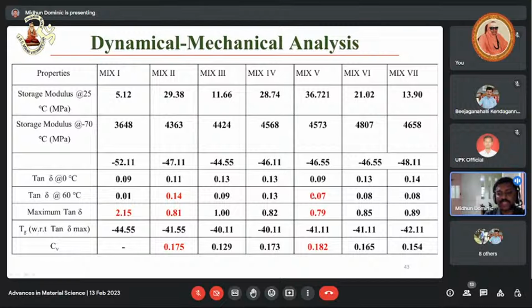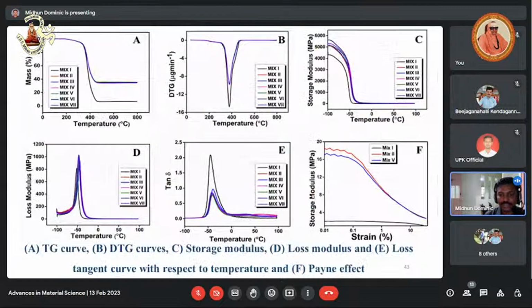About 50% decrease in tan delta at 60 degrees Celsius can be obtained by the synchronized use of carbon black and chitin nanofiber, without compromising the mechanical properties. So these are all the graphs.